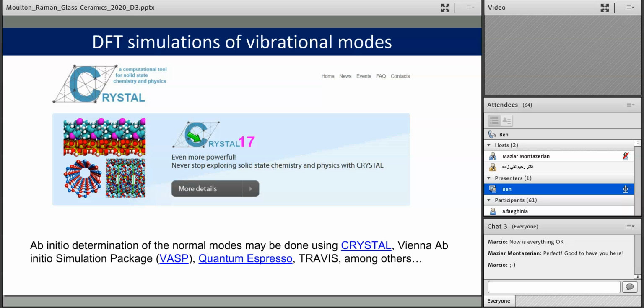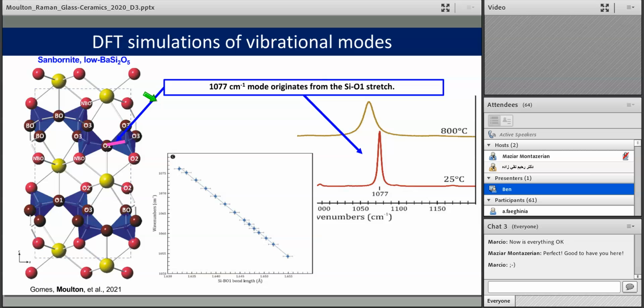I mentioned simulations. You can have various ab initio first principles calculations of the structure. If you have a molecule or you know a crystal structure, you can actually build up that structure from the molecular orbitals themselves and determine it with a fairly excellent degree of accuracy. Probably the most well-known and broadly used is the CRYSTAL program. It's great for crystals, but it's not so good for glasses and other types of networks. This is one that I have worked a little bit with, but there are other options such as the VASP package or Quantum Espresso or TRAVIS. So know that there are options where you can plug in the crystal structure if you know it and determine exactly the origin of the vibrational modes.